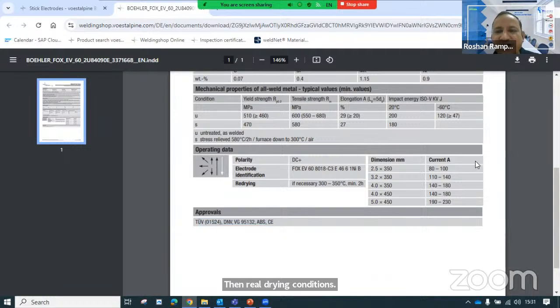It also mentions the recommended amperes for this product for different diameters and lengths. For 2.5 millimeter diameter, 80 to 100 amps is recommended. This is the optimum range. For 3.2 millimeter diameter, 110 to 140. For 4 millimeter diameter, 140 to 180. For 5 millimeter, 190 to 230. These are the amperes recommended for different diameters.